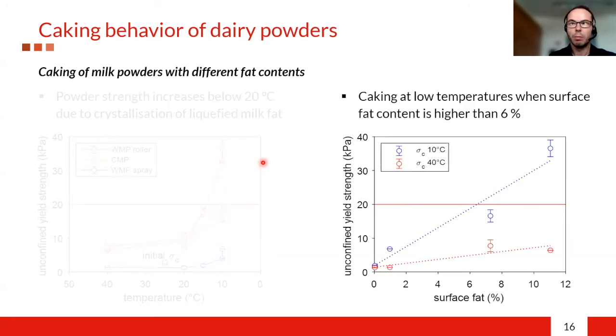We extracted the surface fat from the milk powders with petroleum spirit for 15 minutes to estimate the surface fat content. Here you can see the unconfined yield strength as a function of the surface fat content. At 10 degrees Celsius, the powder strength increases with increasing surface fat content, and at fat contents higher than approximately 6% at the surface, the caking probability is high. So this is what we can keep in mind. However, at higher temperatures, here at 40 degrees Celsius, there's only a low increase in the unconfined yield strengths of the powders.